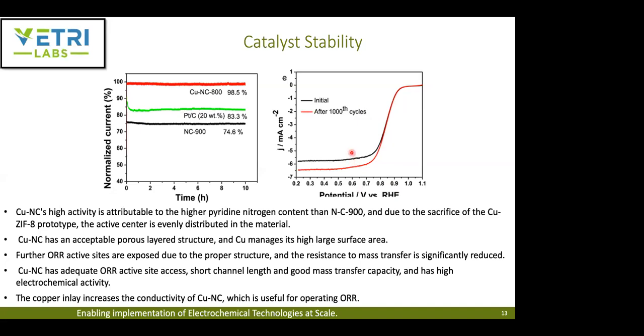Their discussion section says that the initial activity and the LSV after 1,000 cycles kind of overlap, but rather what we see here is that after 1,000 cycles, indeed, they have a higher, increased activity. Which I'm not sure how this could happen. But yeah, so overall, at least based on their chronoamperometry data, they identified that the higher pyridinic nitrogen content present in this copper nitrogen doped carbon is responsible for this higher stability.